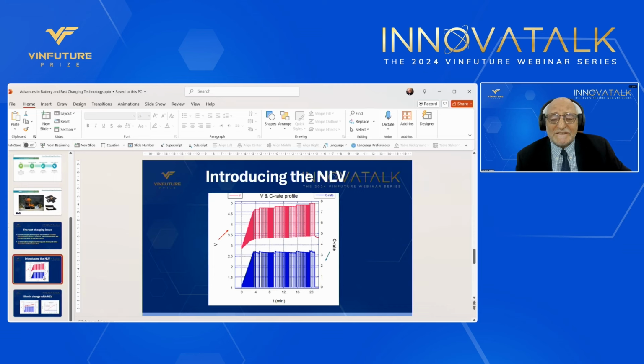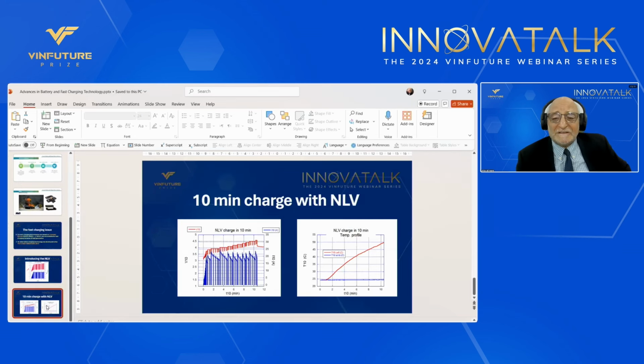Okay, so you can see actually in the red curve, there is a bottom voltage, which we call pseudo open circuit voltage. This is when the current goes to zero. The other point is that the current is never constant. So in this NLV, we apply constant voltage and the current is never constant. So just to illustrate this, we tested NLV on commercial batteries that are used in many devices, including power tools. And we were able to charge this battery in 10 minutes, as you can see on the left-hand side, with the voltage in red and the current in blue. On the right-hand side, we have the temperature evolution during the charging in 10 minutes.